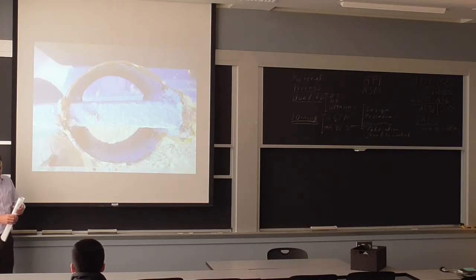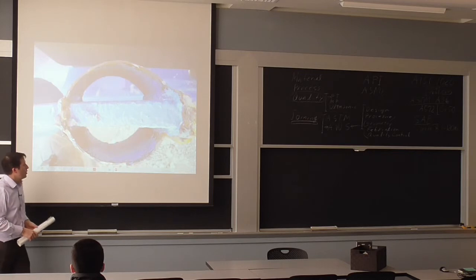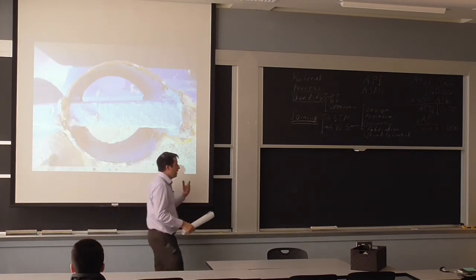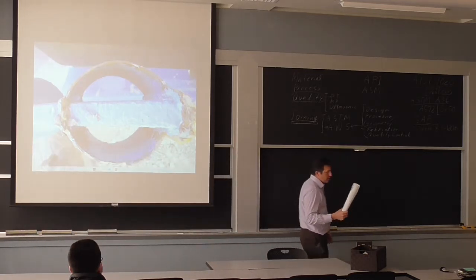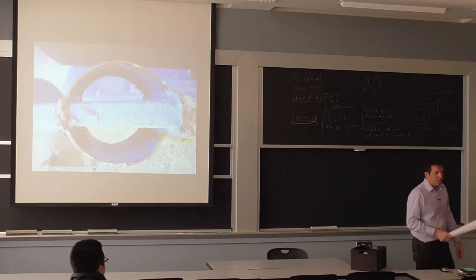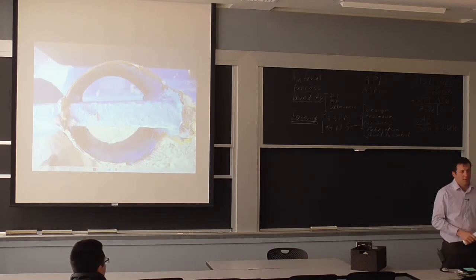So there's still going to be rain or moisture penetrating into that tube. So the real way, and it's described in the AASHTO code for bridges, is you don't weld that corner, because if you do that, you have the bead here loaded in tension, as opposed to just in shear like you'll have on the side. So it's a very simple thought. The idea of having those gussets is to avoid tension in the tube, and now all of a sudden they included them. So that was the reason for these fatigue cracks.